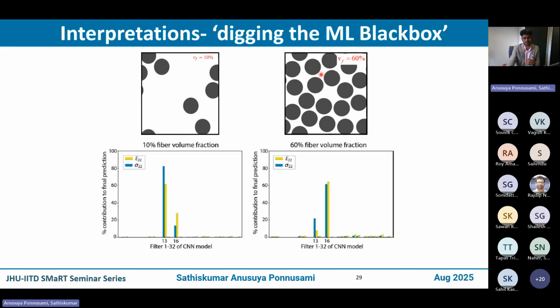It reverses here because the number of fibers is more, so you see the fibers peaking here rather than the matrix. Obviously, you see many more little blips here, which means there are other features that the model extracted, but they are not considered really important or significant for the predictions. But if you want to extrapolate to complex microstructures, such as what if the microstructure has pre-existing defects or flaws? In that case, those features might assume importance, and that is where you might see potential third and fourth peaks that might have an impact on the predictions.